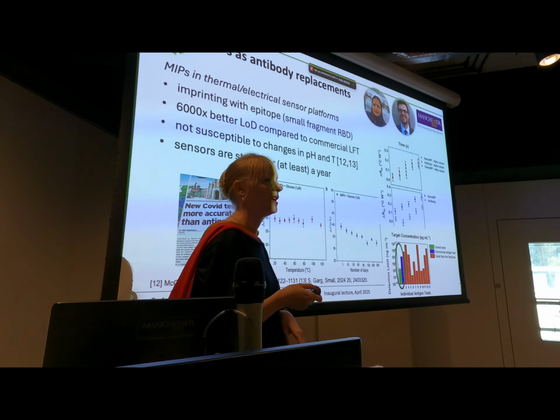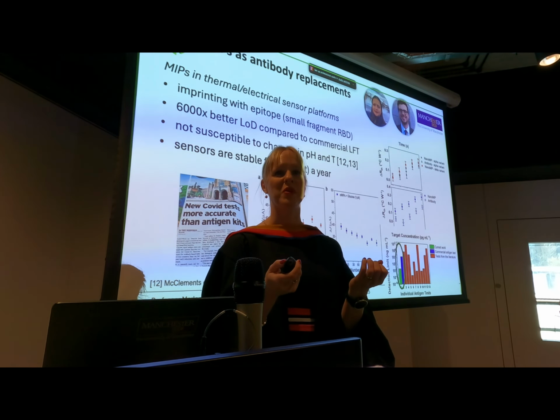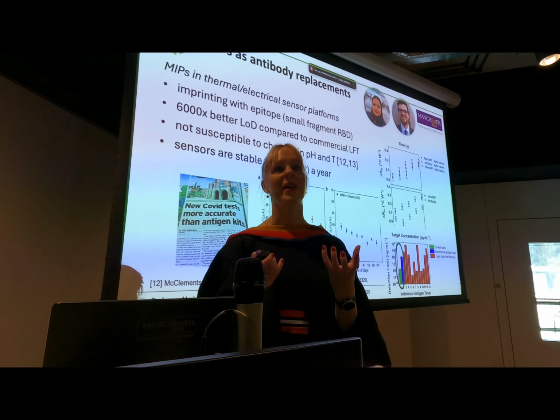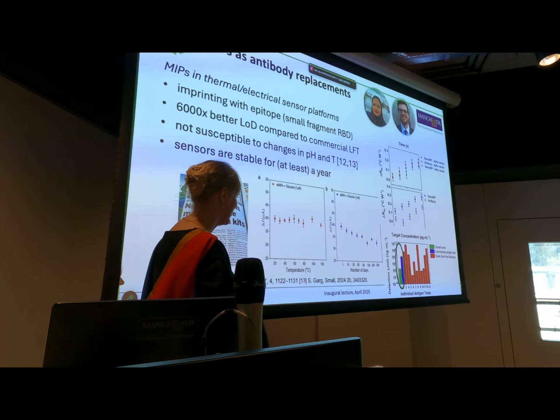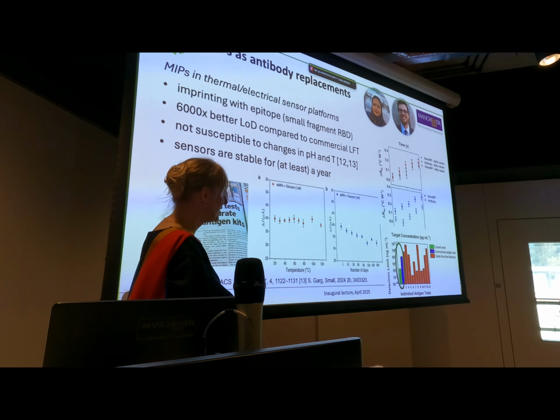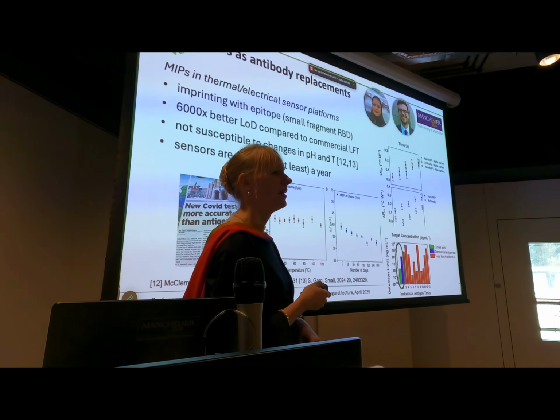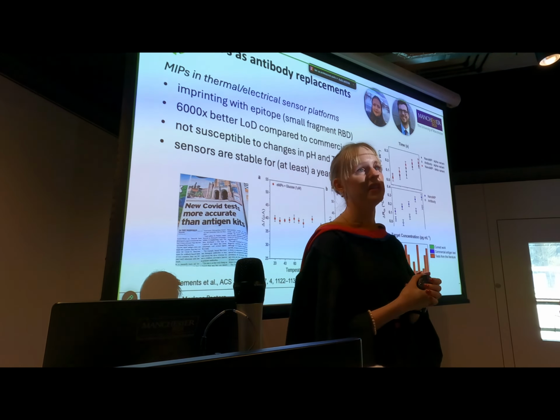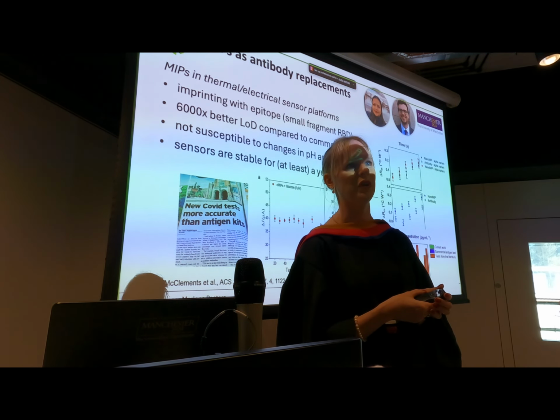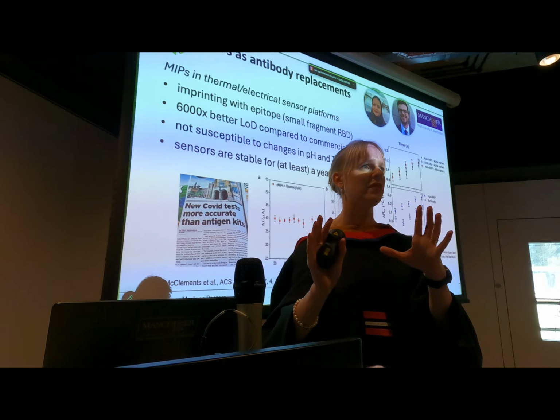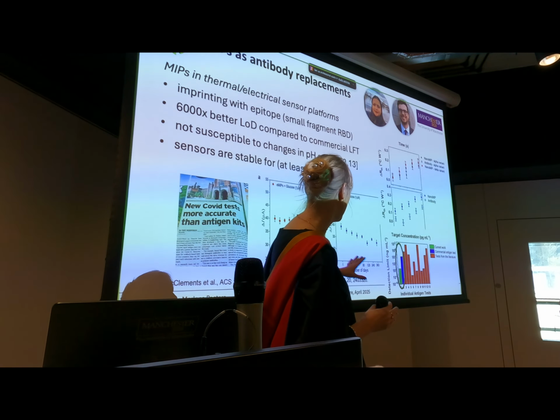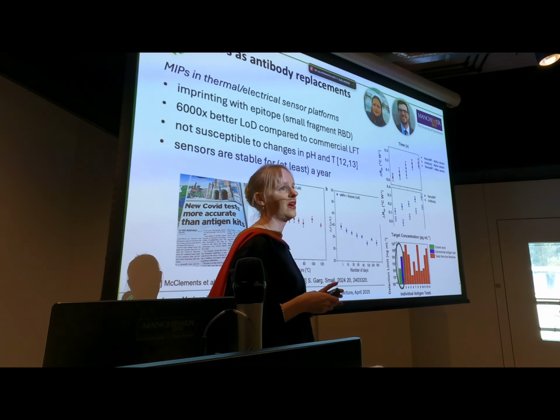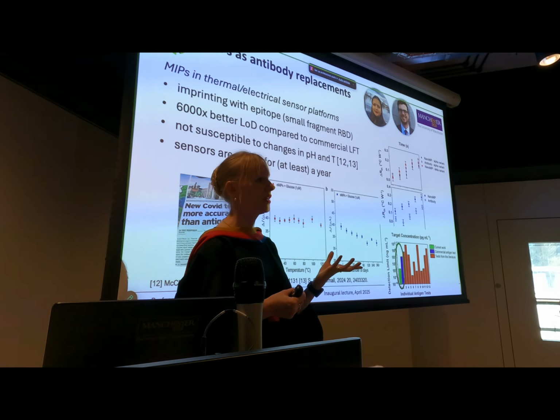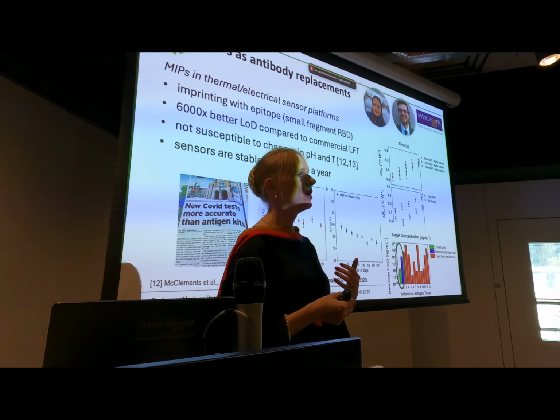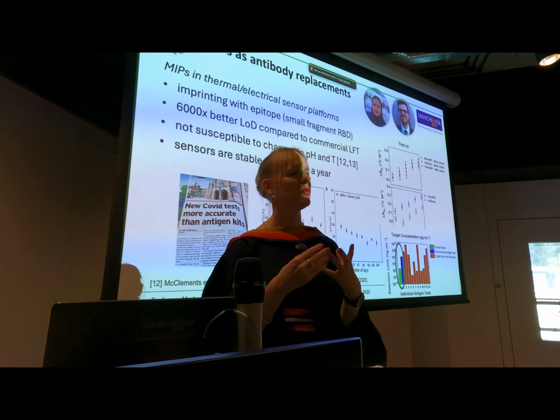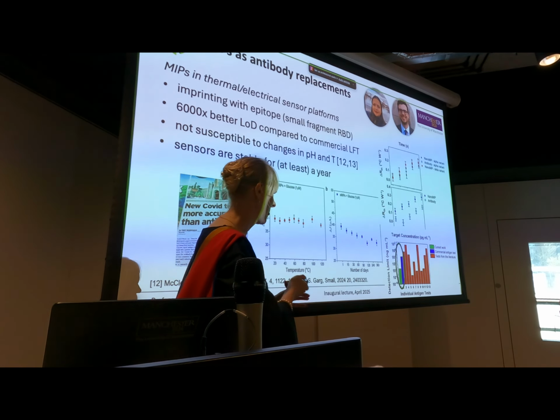And then the other thing, which is what Sveta looked at, what happens if we store these sensors? How long can we keep them for? Well, in essence, a long time. So she managed to take them for over a year, and you don't need any special storage conditions, which is the other really important advantage of these polymers. You don't necessarily have to stick them in the fridge. You can just keep them at room temperature, and you can see there was hardly any change. And that's obviously a big advantage if you look at resource limited settings, or very hot climates, or anything where you don't have these very specific conditions.